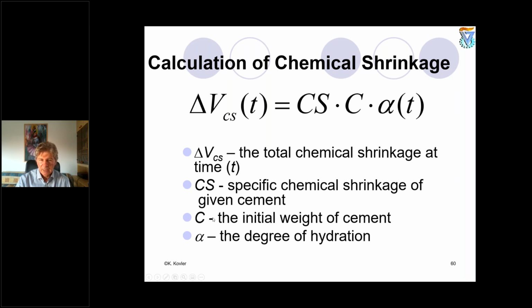C, capital, is the initial weight of cement. And alpha is the degree of hydration. Yes, we admit that alpha is not 100% because we are speaking about the first, let's say, 1 week of the concrete age. In 1 week, we don't have 100%. We are still below 100% in our experiments. In 1 week we have approximately 60, maybe 70% of hydration, but not more. And this should be considered in calculating the chemical shrinkage.